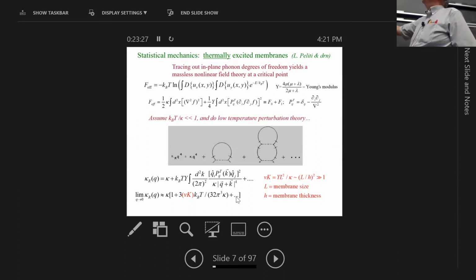And so that's what I'm symbolically representing here. You sort of do a partition function, integrating over those in-plane phonons. This is the energy that I was talking about, this nonlinear energy. And when the dust settles with this little calculation, there's an effective free energy that still has these very soft out-of-plane phonon modes with the bending rigidity here. And then there's a transverse projection operator that actually makes the problem highly non-local, acting on these derivatives of the out-of-plane tilts. So these little gradients, you can think of them as being like tilts of the Heisenberg order parameter. This is what allows this thing, it turns out, to have long-range order.